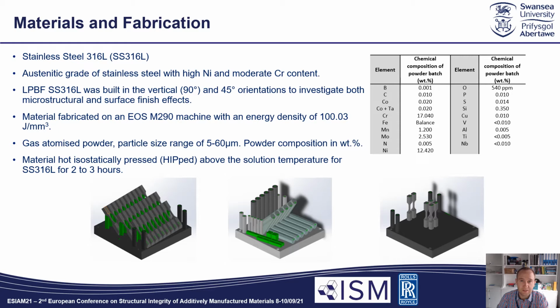Post-manufacture, all the specimens were subject to hot isostatic pressing for a few hours at an elevated temperature above the solution temperature to alleviate any porosity left over from the processing steps.